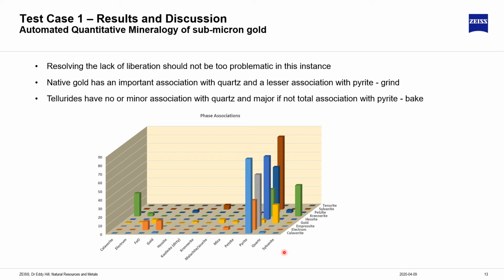The tellurides have no or minor association with quartz, as we can see for the rest of the samples along this row. However, they have major associations with pyrite. And in this instance, if we do want to recover the tellurides, we would recommend baking.